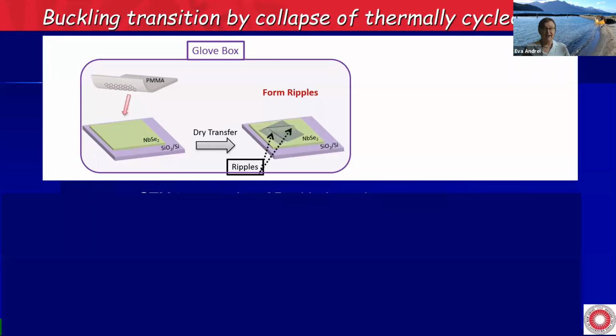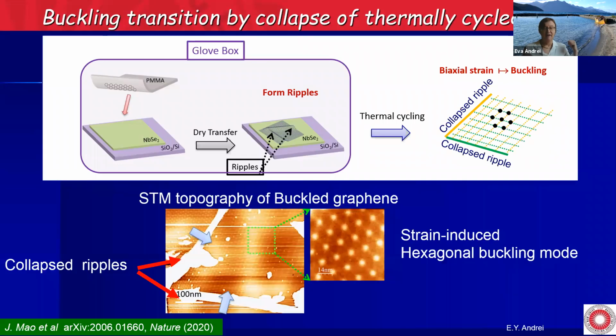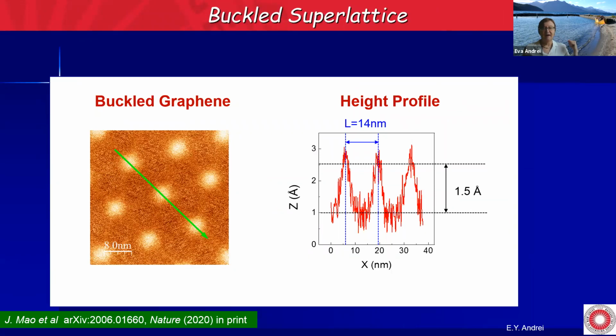And we were actually able to do this. We have a graphene layer that's deposited on a niobium diselenide sample, and after heat treatment, there were two ripples that were pinned, which were able to apply compressive strain. And the bottom line is, at the end of the day, these are the two ripples, and this is zooming in to this buckling structure. We obtain a beautiful periodic strain-induced hexagonal buckling mode. And it's beautifully periodic. Here is the out-of-plane profile, it's about 1.5 angstrom. The period in this case is 14 nanometers. We have periods running from 9 nanometers to 25 nanometers.